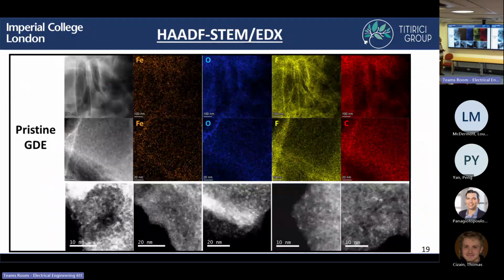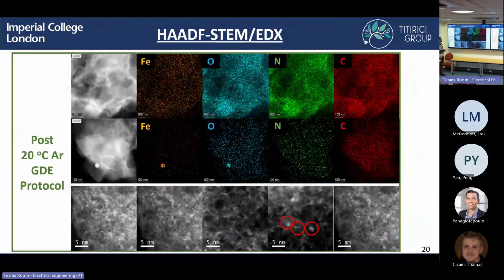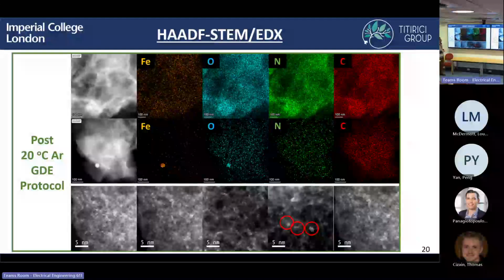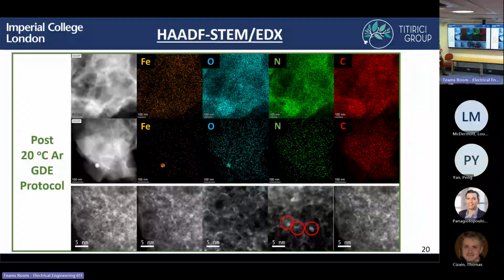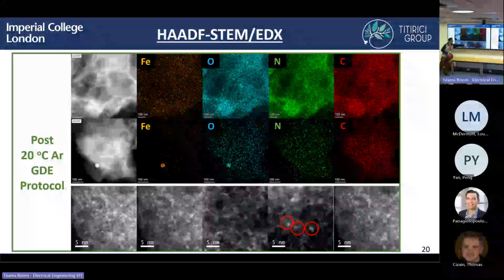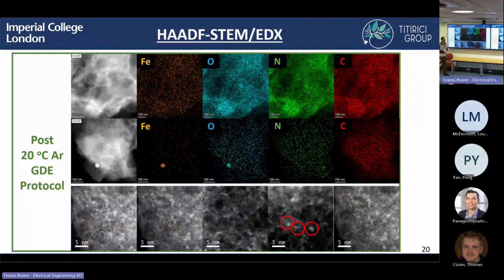And so looking at the pristine material, we can see still that the iron is atomically dispersed, and we don't really see any nanoparticles within the material. So once we've made the electrode, it's still atomically dispersed. And after the argon protocol at 20 degrees, we see that it's still mainly atomically dispersed, but we do see some areas of iron and oxygen overlapping and some very small iron clusters. But these are a fairly low concentration.